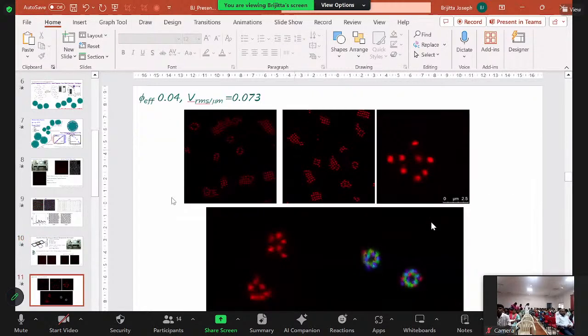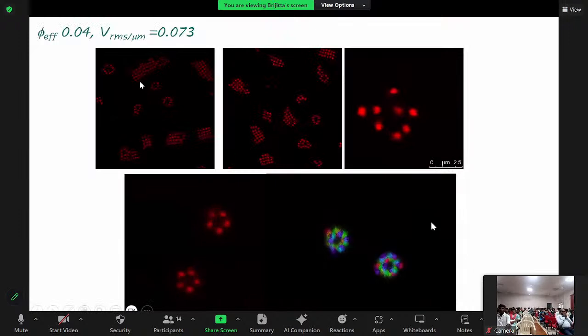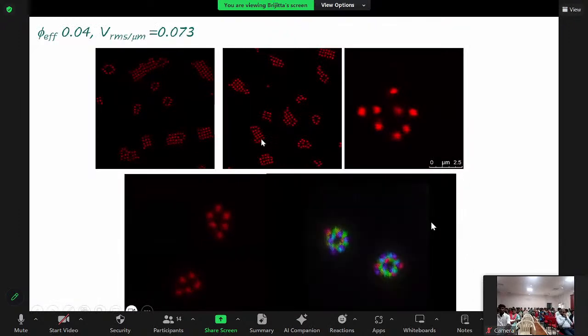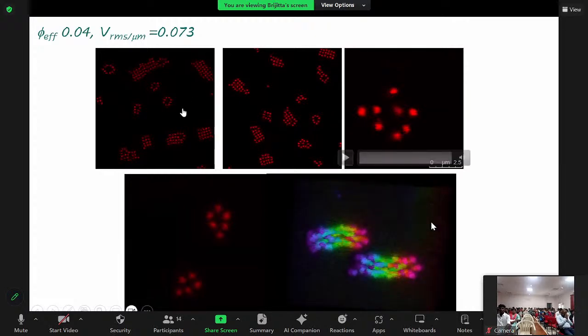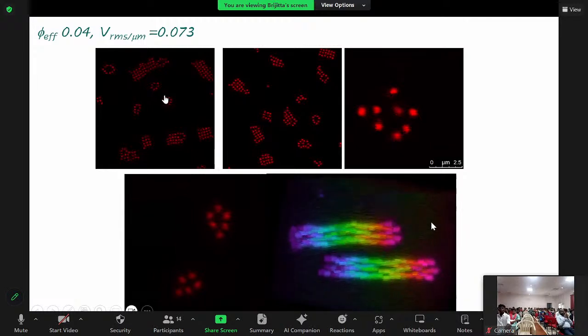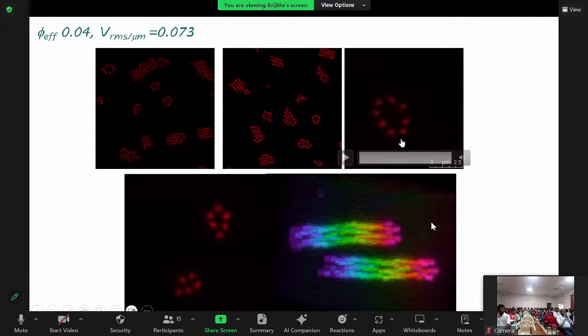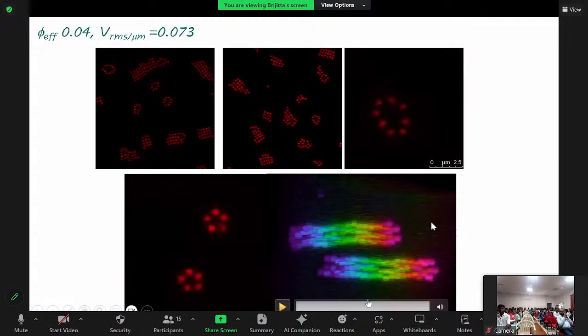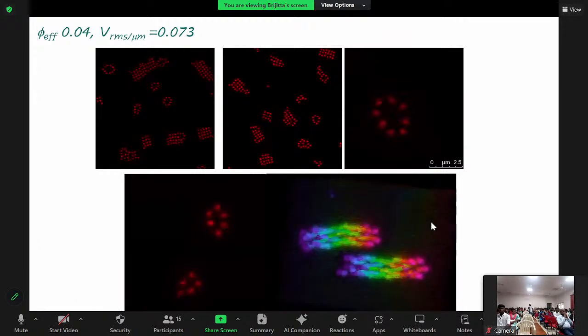Next, we also came upon an interesting observation: with sufficient concentration, the particles can form crystalline structures. Here you see the body-centered cubic arrangement of the particles, BCC. But in addition, the particles can also form rings. If you take a paper and fold it and look at it from the top, it looks like a ring, but essentially it is like a pipe or a tube. What we see on the top surface is the ring, but in 3D it is a tube. Here you can see rings in two dimensions, and here I have made a 3-dimensional reconstruction of about 20 planes, and you can see they are actually tubes.